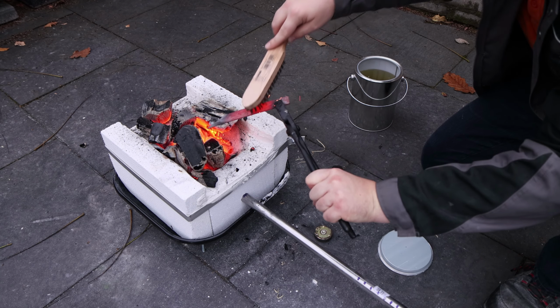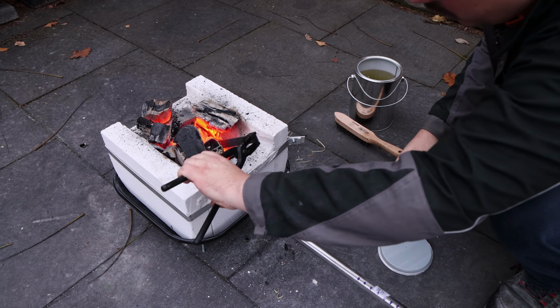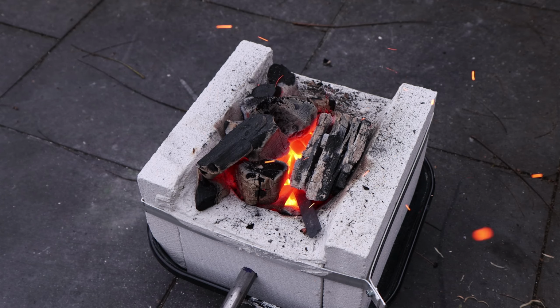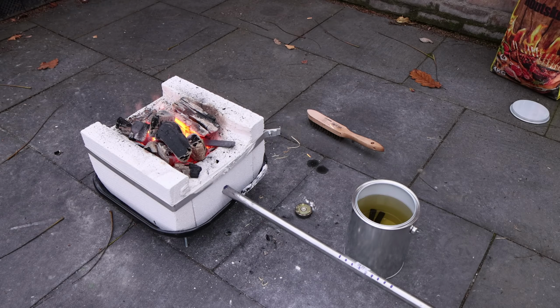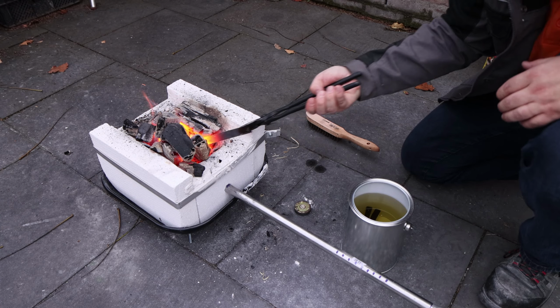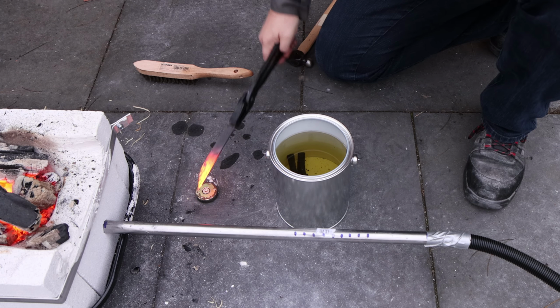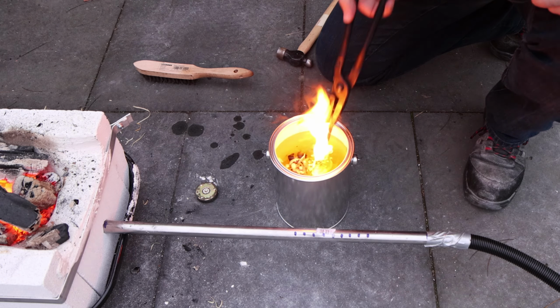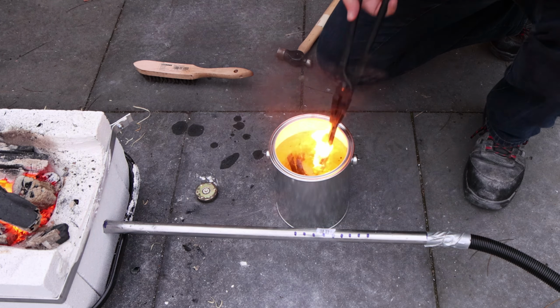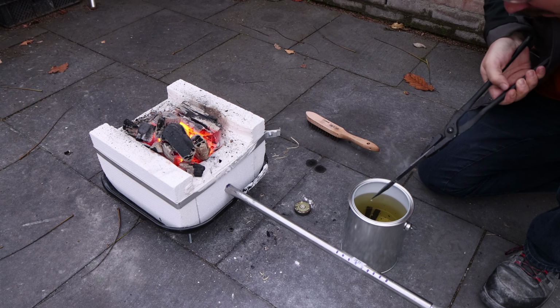Anyway, I first heat the whole thing to oxidize it and to get a nice dark color on the blade, before concentrating the heat on the edge by putting it in halfway. When it seems hot enough, I check for magnetism. This wasn't there, so I dunked the blade in the warm oil for 10 to 15 seconds. It didn't warp, but inspecting the knife after quenching, it seems that the thin edge might have burned.